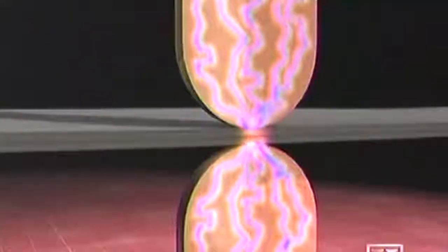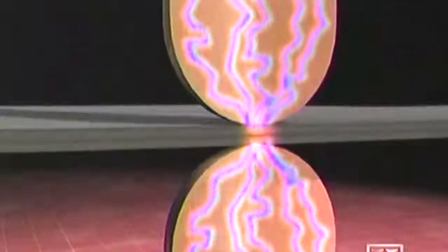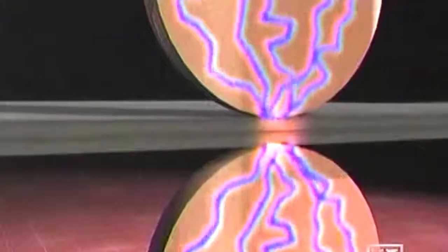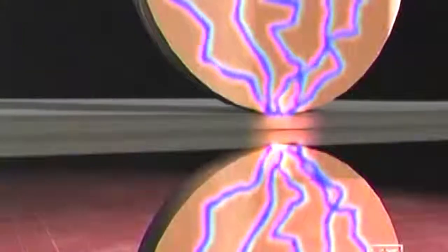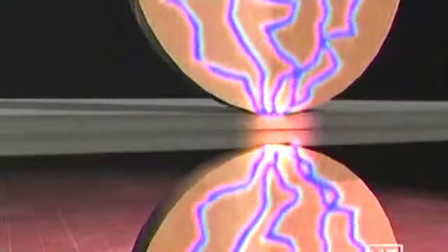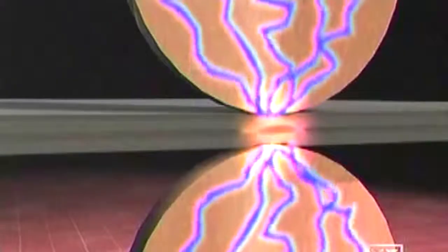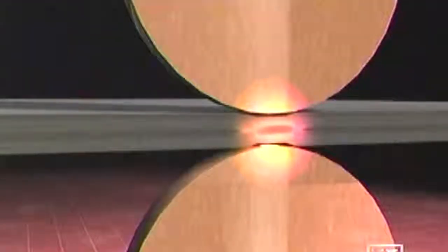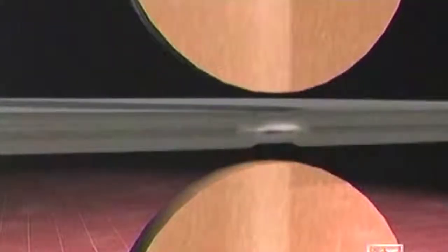You need pressure. When the two electrodes come together, they pinch the two metal sheets at the spot and cause a small indentation in both. Electric current then begins to pass from one electrode to the other through this spot in the sheet metal. As it does so, the current that flowed so smoothly through the copper now encounters resistance in the less conductive metal pieces. This resistance results in heat, and the metal begins to melt, causing a molten nugget to form. When the molten nugget cools and coalesces, it locks the two metal sheets together. The electrodes then release the pinch point and move on.